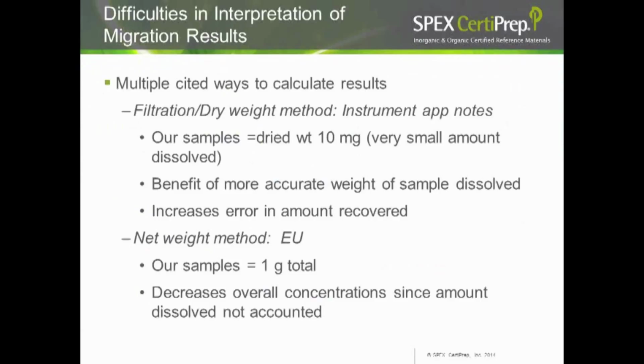Now, there is potentially the benefit because you're seeing the actual portion that migrates into the matrix, but anytime you have to dry and reweigh your samples, you exponentially increase your error. The more common way of looking at it, and the way prescribed by the EU, is looking at the total weight of the sample, or the total weight of the plastic that you put into your extract. For that, that was 1 gram. This overall takes your results, though, and spreads them across that 1 gram sample.